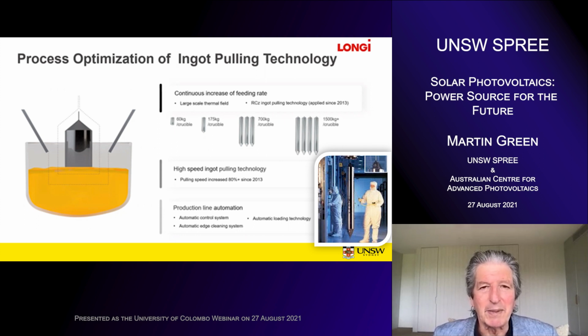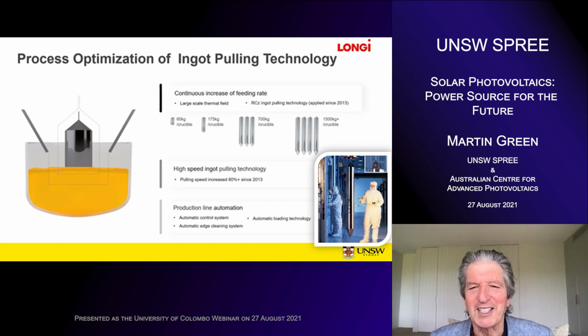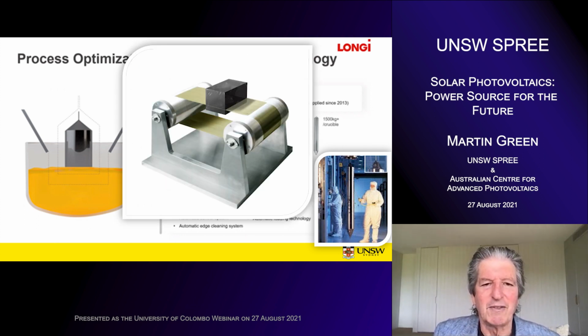But what's been happening is people have been making better and better quality silicon so they can make better and better cells. The industry is so big now that you've got big companies working on these technologies. So instead of just growing, like a few years ago, just one crystal of silicon from the melt, what happens now is the melt is recharged between growth of crystals, and from one container now there's 4 or 5 crystals grown. So instead of getting 60 kilograms from one container holding the molten silicon, you're now getting about 1.5 tons from that container of similar size and cost. So that type of thing is greatly reducing the costs of photovoltaics.